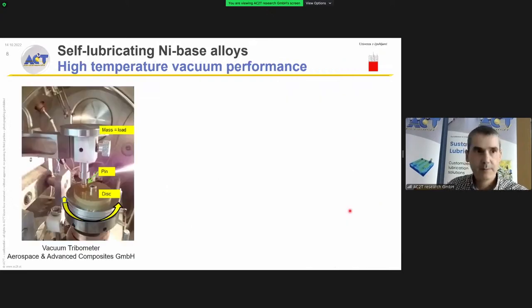But where these nickel-based materials really shine is in vacuum. So in vacuum, we tested against 440C, the martensitic stainless steel. This is the reference material for vacuum experiments. And this is a pin on disc, but don't be confused because it's not unidirectional. It's reciprocating sliding, so we are moving around an arc of circumference with a constant normal load and at 2 different temperatures, room temperature and 300 degrees, without any solid lubricant, without lubricant at all.